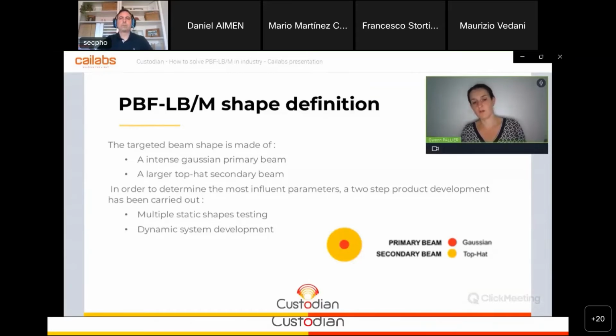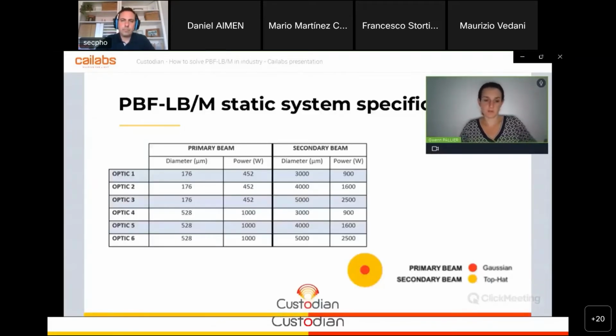So what were the static systems that we have developed? Well, we have decided to actually develop 6 of them with different parameters. So first of all, we have tried 2 different primary beam diameters. One was 180 micron diameter, the other one was 530 micron diameter. So that was for the primary beam diameter.